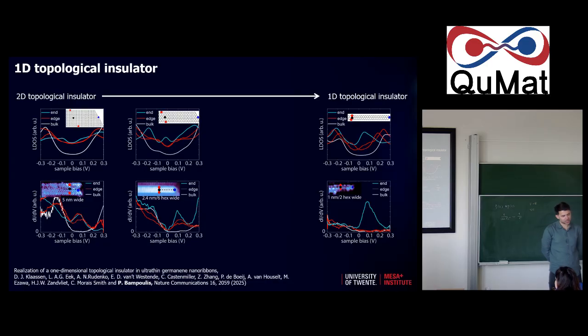Maybe I start with the nanoribbons part. There are only 2 papers for nanoribbons, and both use more or less the same growth, so both need this metal below. But what I should point out is that if you look at the regions where they're a little bit more isolated compared to these parallel arrays, the surface around it is semiconducting. And you have a gap that is a little bit smaller than the bulk germanium gap, in the range of 0.4, 0.5 eV. So that could be a place where you could think of putting some contacts and making a device, because then any parasitic current from the metal would be suppressed compared to a system that is on top of the metal, where it's a bit of a game over.